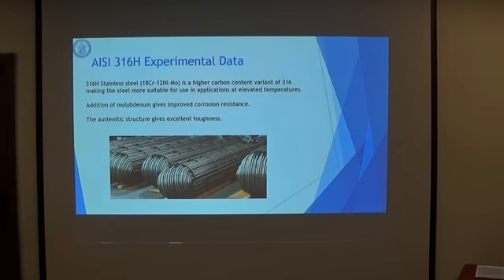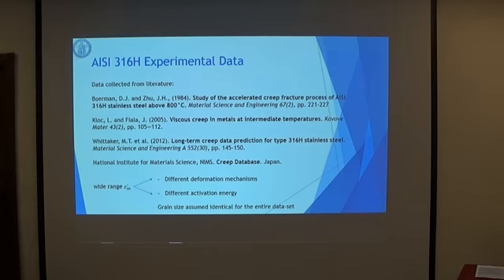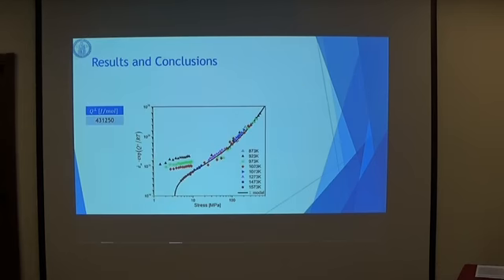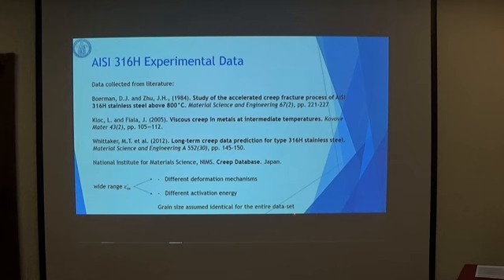So in order to validate this model, we found some data in the literature related to the 316H stainless steel. The data are mainly from Boerman and Zhu, Kloc and Fiala, Whittaker, and by the Japanese National Institute for Material Science. We have a wide range of minimum creep rate, and we are sure that there are different deformation mechanisms which are activated by different activation energies.